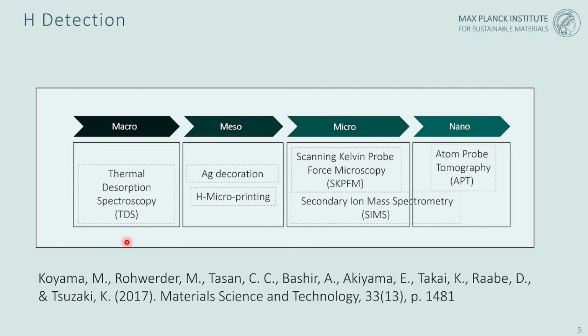The standard approach for doing so is, of course, the use of thermal desorption spectroscopy, TDS, in which you associate certain evaporation peaks during the desorption with certain trapping energies. But these peaks are often very broad and overlap and are not so easy to disentangle.